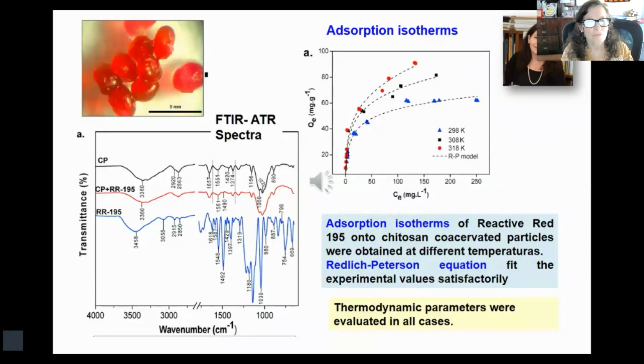We can observe the FTIR spectra of the coacervated particles before and after the adsorption process. Also, the adsorption isotherms that were obtained at different temperatures. The Redlich-Peterson equation fit the experimental values satisfactorily. Thermodynamic parameters were evaluated in all cases.